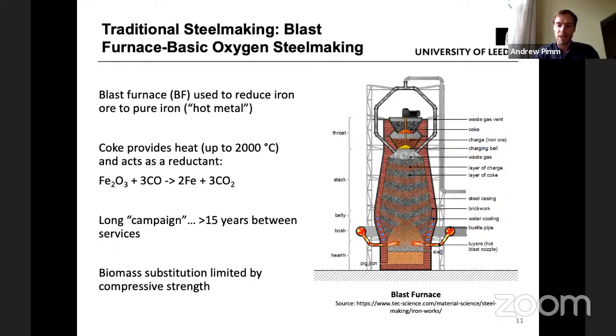So there's a schematic here, hopefully it doesn't change, there we go, a schematic of a blast furnace, which is, as I said, used to reduce iron ore, iron oxide, to pure iron, which is known as hot metal. So coke, as I said, a concentrated form of carbon derived from coal, is used to provide heat up to something like 2000 degrees C, and it also acts as a reductant. And the chemical formula given here shows you what happens: iron hematite, Fe2O3, which is your iron ore, plus carbon monoxide gives you iron and carbon dioxide. So yeah, as I said, very high levels of CO2 emissions.